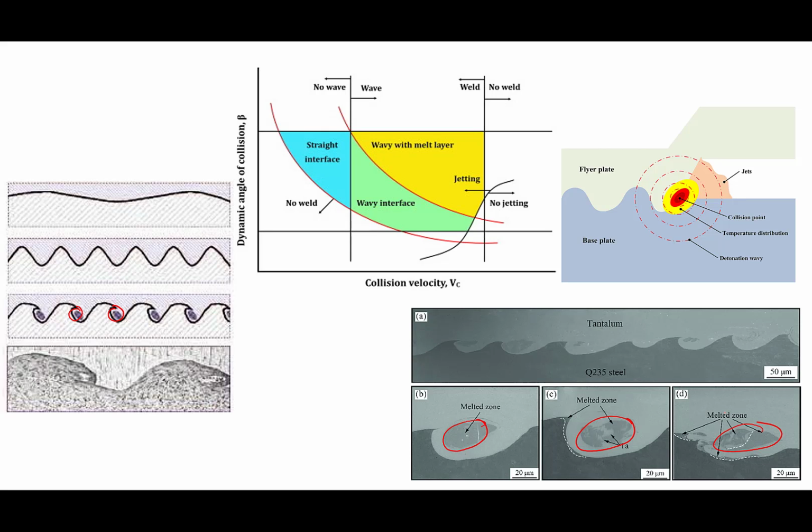Basically, the zone around these interfaces will certainly be deformed. All the metals in the vicinity of the interface will experience the effect of deformation. There will be high dislocation density. So if you check the hardness distribution across the interface, you will always find that near the interface the hardness is high, while away from the interface it is lower. That will be the situation in all cases.